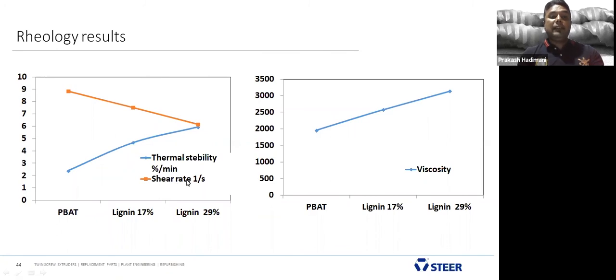But shear rate wise, in the screw, what's happening? PBAT is giving a higher shear rate. The addition of lignin, interestingly, reduces the shear rate slowly. That shows the mixing was good, but the shear rate was lower. This is where it is taken for the FGT technology.